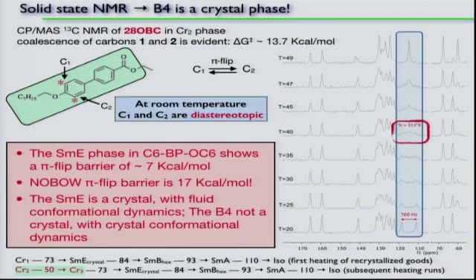So the whole reason for doing these experiments was based on a wrong assumption, which is you don't get reflection symmetry breaking in achiral liquid crystals. Actually, you do. But I think in the B4 case, it's much more like a crystal. So with the solid state NMR, you can, well, okay. It turns out physicists invented NMR, but they haven't really kept up with it very much. And it's become the tool of chemistry, right? As opposed to a microscope, we use NMR to determine structure. And you can use solid state NMR.